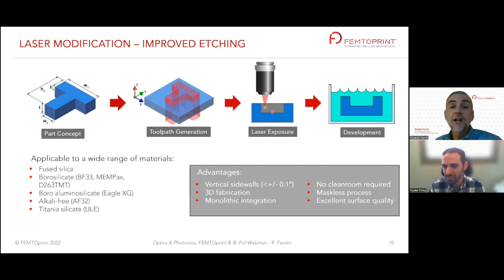Once the glass is fragilized, it means it is much more sensitive to what? To etching. So we go into what we call material processing. It's an etching bath, and we remove the glass that has been fragilized. So for example, here you see we create a cavity, but we can also create 3D shapes. We can open channels, and that's how we print into glass. It's a two-step process that can be applied especially for fused silica.